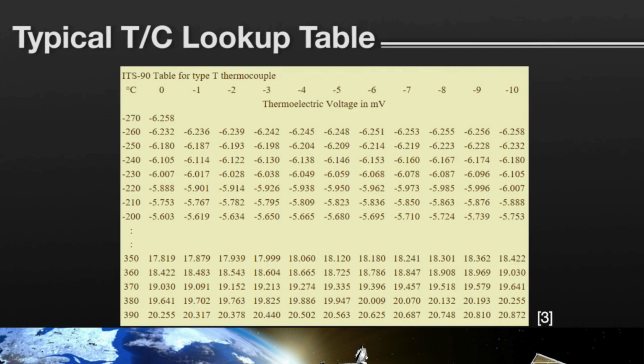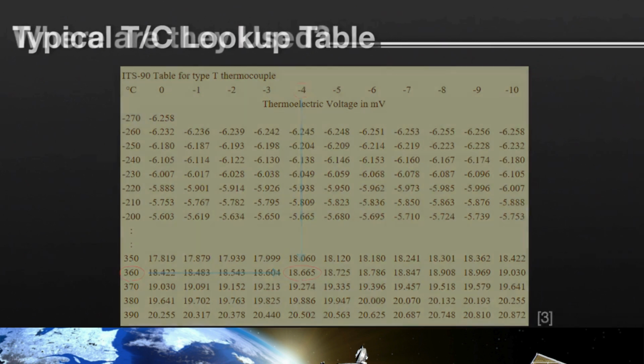For example, to find the thermoelectric voltage for 364 degrees C, you first find the row corresponding to 360 degrees C, and then the column corresponding to 4 degrees C. And at the intersection of those rows and columns, you read 18.665 millivolts for the thermoelectric voltage.